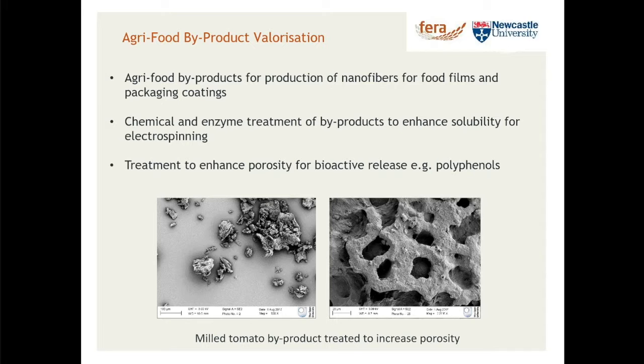What we've tried also to do is treat some of the agri-food waste to make it a bit more soluble, because to spray the liquid, we have to be dealing with soluble or partly soluble materials, or smaller materials, so they can actually be sprayed. And so we've looked at chemical and enzyme treatments of these materials to enhance their solubility. But another reason for doing this is that some of these agri-food waste materials, if we're trying to get them to release some of their active compounds, such as polyphenols, which also have antimicrobial effects, or maybe antioxidant effects, again, perhaps treating some of these materials chemically or with enzymes will help them release those materials. So fully trying to maximize the benefits of using these agri-food wastes.